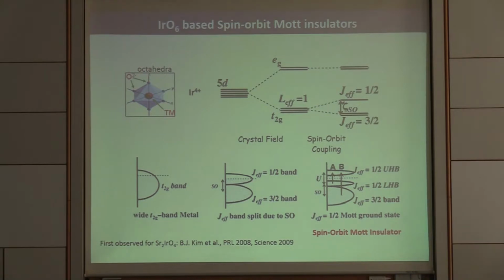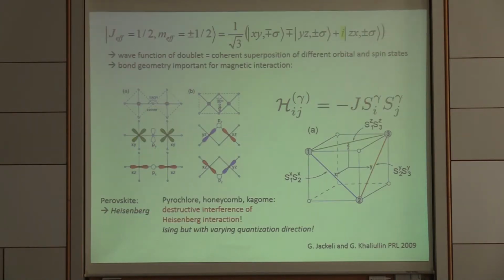So the reason for that is a large spin-orbit coupling, which splits this t2g into a J-effective 3/2 quartet and a J-effective 1/2 doublet. And now the moderate Coulomb repulsion is able to induce a Mott insulating state for this half-filled J-effective 1/2 band. And that's the scenario of the spin-orbit Mott insulator, which has been proven, for instance, for this layered strontium iridate material.